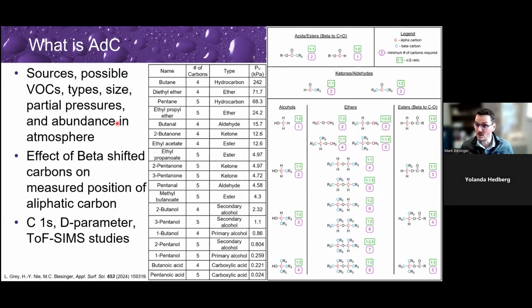It's not going to be big molecules. It's going to be short stuff. So what volatile organic components are in the air? They have certain partial pressures and those sorts of things that are available. They're going to have different sticking coefficients, different sizes, more carbon. There's not going to be as many of them. One of the things that we thought about a lot is, how does the effect of beta shifted carbons affect the apparent positioning, using our standard fitting, of the carbon-hydrogen peak? And so what is a beta shifted